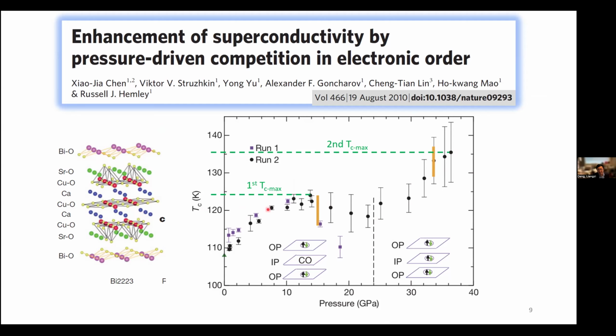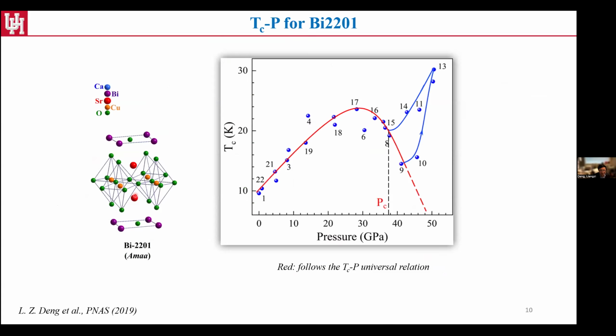So triggered by this, the work we were thinking is, does it have to be the only reason that gives the second resurgence, that it really has to be tuning the inner layer? One of the relatively easy measurements, even though it is a lot of effort, is to go back to the single layer Bi-2201. If the only reason is that we have to have this outer layer, inner layer sandwich model, then we should not expect to see another Tc resurgence, even though we wish, right?